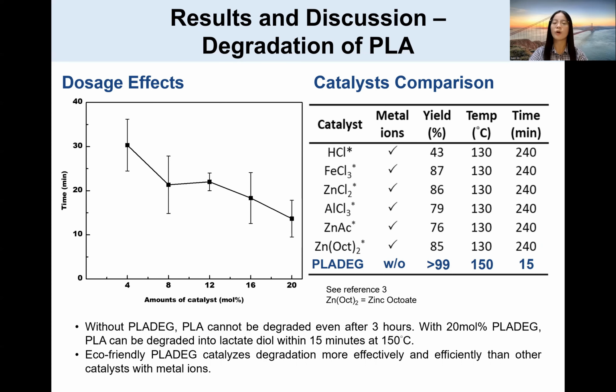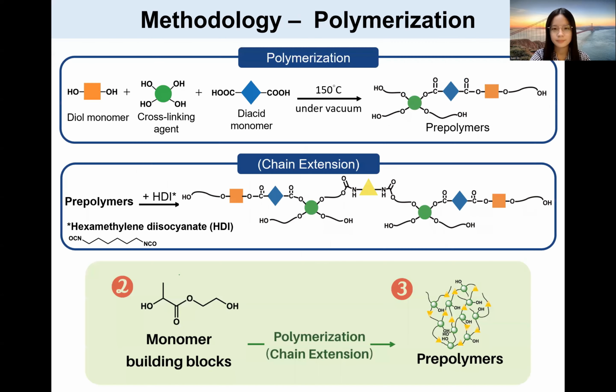Now, how do I know that PLA-DEG is really better than the other catalysts proposed by previous studies? It's better than the other catalysts in 3 aspects: more eco-friendly, more effective, and more efficient. It's more eco-friendly because it does not contain any metal ions. It's more effective as shown in an over 99% yield of lactate diol, the monomer. And it's more efficient. PLA can be fully degraded within just 15 minutes. Compared with others, PLA takes 240 minutes to be completely degraded. That's a huge difference.